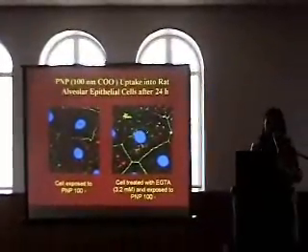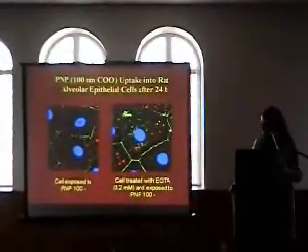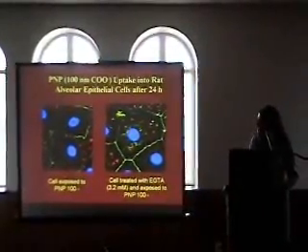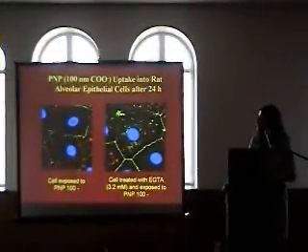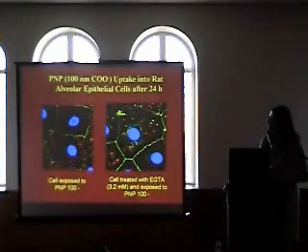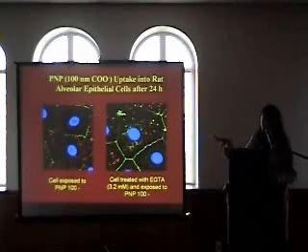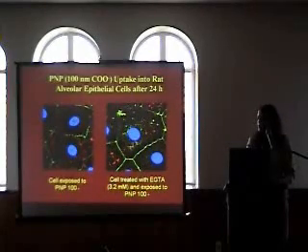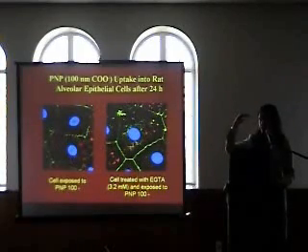For discriminating between paracellular and transcellular pathways, we did confocal microscopy. This is the mid-section confocal micrograph of cells exposed to carboxylate-modified 100 nanometer PNP, and you can see that these nanoparticles are mostly inside the cytoplasm and not on cell-cell junctions or nuclei. I have done a Z-stack, and from the top of the cells to the bottom, they are still inside the cell.